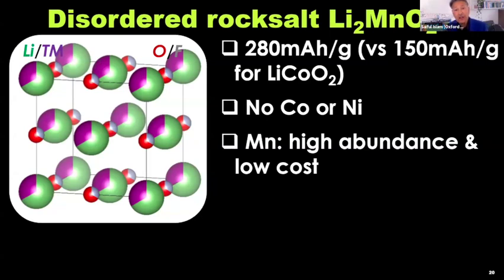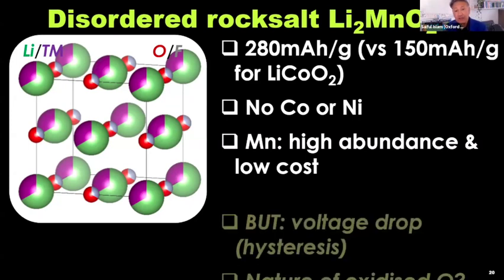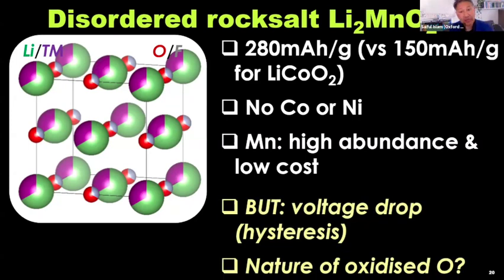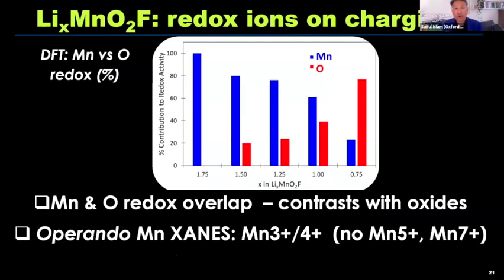This shows a higher energy capacity at first cycle than the lithium cobalt oxide. As I mentioned before, there's no cobalt or nickel, which is a plus. Manganese has high abundance and lower cost. But these materials don't work as well as lithium cobalt oxide or NMC. They've got a voltage drop called a hysteresis, and the nature of the oxidized oxygen is not well established. So let me start off with some simulation work.